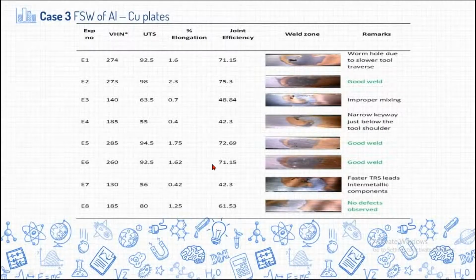We cut pieces from the particular experiments and did optical evaluation, like experiment 1. There is a wormhole effect due to slower tool traverse speed, and some good welding for experiment number 2 parameters. See the ultimate tensile strength, UTS, also good, and good quality welding obtained. Some other defects were observed over here, and the tensile strength is also less here. And these are all good weldings and no defects observed over here.